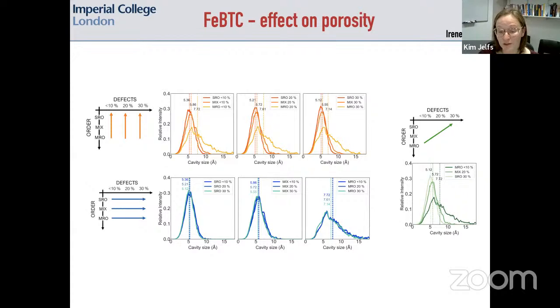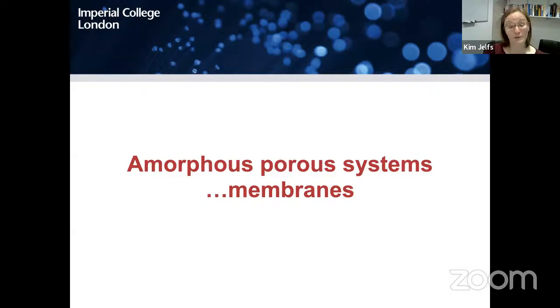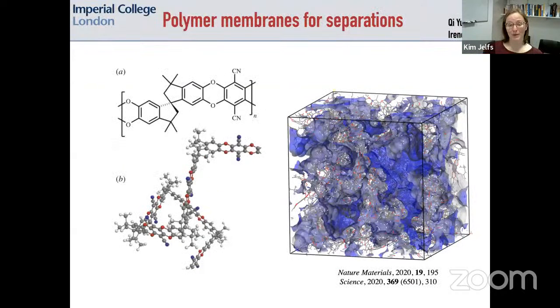if we're just looking at pore size distributions, although of course changing the level of defects will have a much stronger influence on other properties beyond porosity. And so in the green, we go across that graph where we're changing both order and defects at the same time. But really, now to get to the polymer membranes.